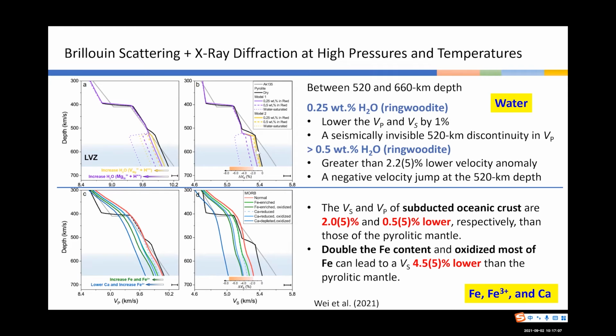So this amount of water can only lower the shear wave velocity, Vs, by only 1%. But from seismology, they observe more than 2%, that is, a 2 to 7% reduction in the shear wave. So in this case, if water is present in the octahedral sites of the ringwoodite, it's impossible to use the water in the transition zone to explain the low shear wave velocity anomaly.